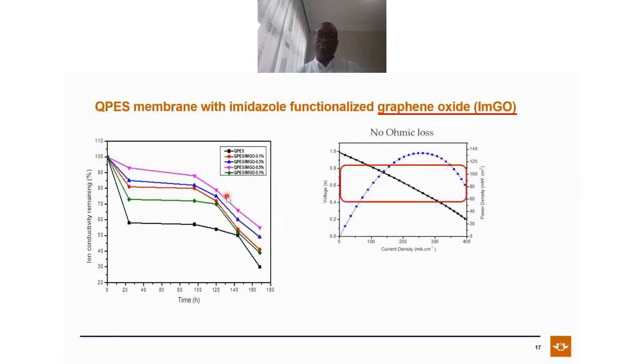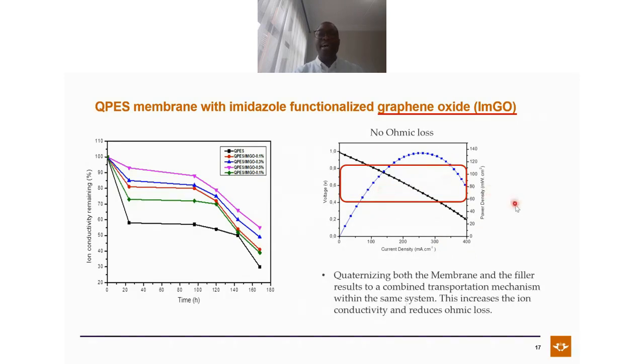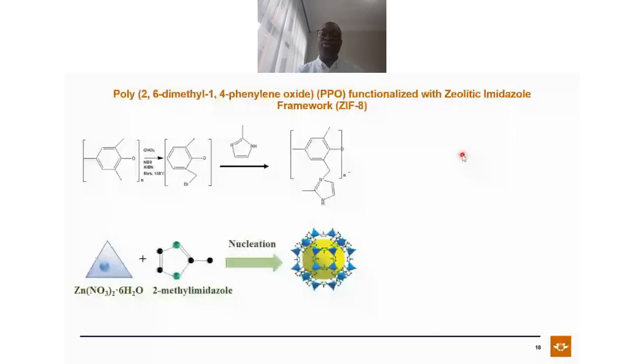But I want you to come back to this part. Remember when we spoke about the performance of your fuel cell, we said we have 3 stages of losses, and we're focusing on ohmic loss. As you can see on this performance, we do not have any ohmic loss due to the membrane. What does that tell us? Well, this tells us that the membrane is able to move the OH minus faster across it. So there's no drag. That's why we're not seeing any ohmic loss. As you can see, we had one of the highest outputs, above about 130 milliwatts per square centimeter of power. So basically, quaternizing both the membrane and the filler results in a combined transportation mechanism within the same system. This increased the ion conductivity and reduced the ohmic loss.